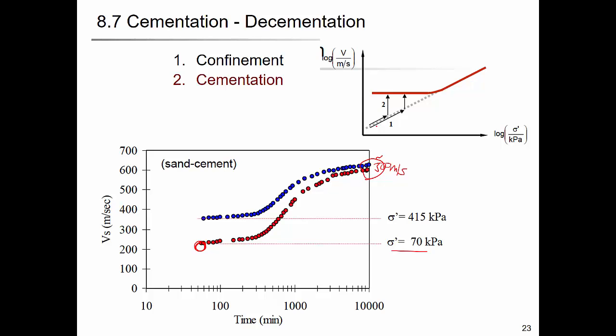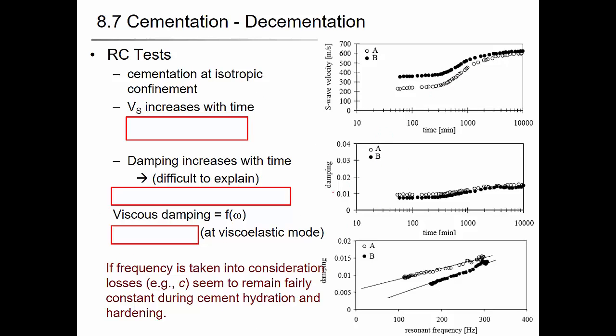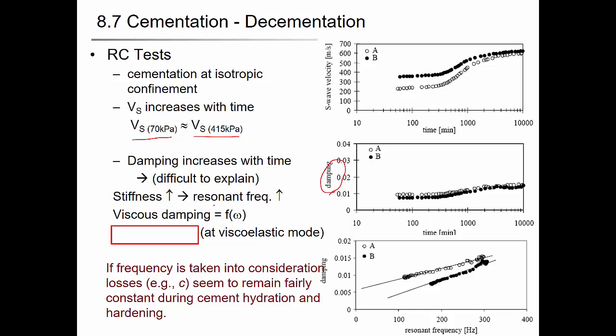And this tells you that if you apply the stress first and then the cement gets cured, you will have an increase in wave velocity during procedure two. So procedure one is the confinement, procedure two is the cementation. And they also measured the damping, and you can see the damping increases a little bit with the cementation. So the Vs at 70 kilopascal and Vs at 415 kilopascal were similar to each other. And the reason that we have increasing damping is very difficult to explain, because when you have a stiffness increase, the resonant frequency increases. Right? The soil gets stiffer, so the natural resonant frequency increases together.